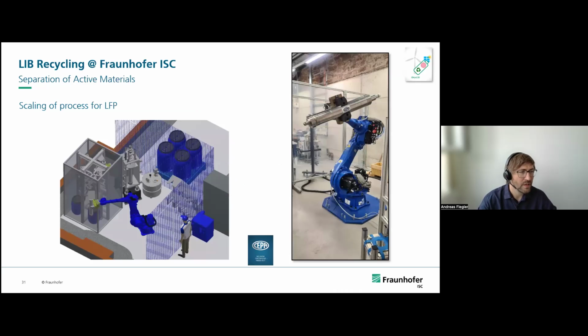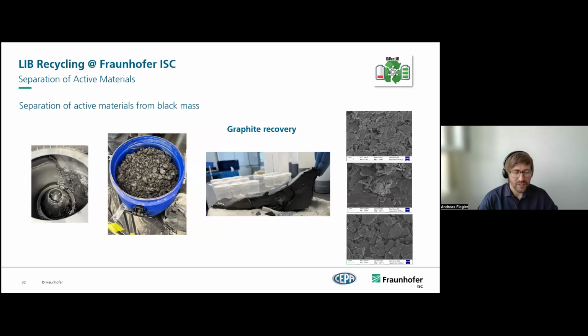And to prevent this, we built up an automated process. So we use a robot which can bring the cylinder into the centrifuge, and then into a cleaning section which runs automatically. And so we can transfer this process from a semi-continuous to a quasi-continuous process. What we see with this centrifuge type is that we cannot recover materials with a higher density or with a higher particle size. For this, we developed with our partner SEPA a new centrifuge type. It's a drum centrifuge, and with this we can separate graphite materials from black mass and also NMC materials.